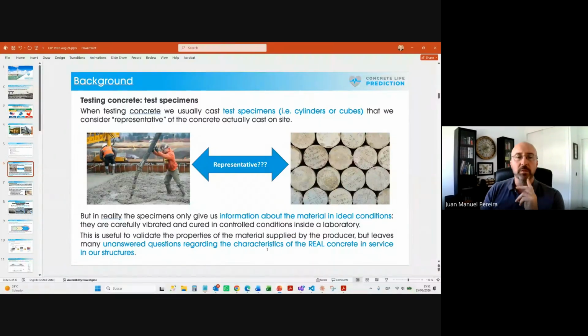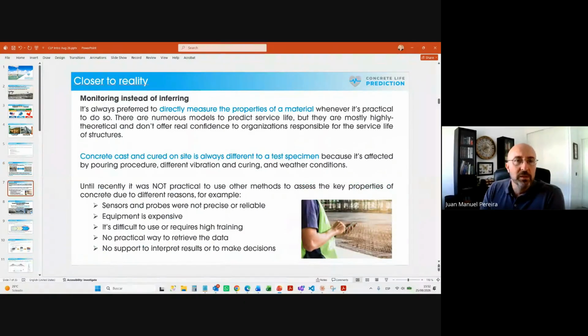Okay? And the important thing is that we do monitoring, because monitoring is much more representative than cubes or cylinders or samples that you can take on site. Then you cure them in the lab, so they are cured in lab conditions. It's not real site conditions. There's also the chain of custody: how the concrete was sampled, how it was cured, how it was transported, tested, etc. Okay. So we consider that monitoring is much more representative of the real concrete in the real structure, in the real conditions. Okay, again, this know your concrete concept.